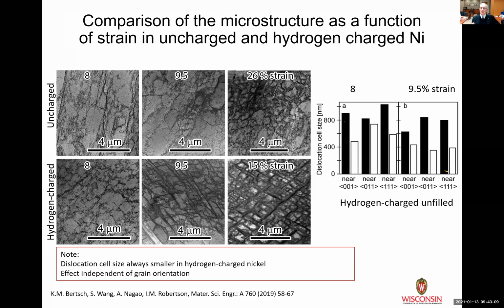You must compare microstructures in the same grain orientation. So one of the beauties that you have today is that you can do EBSD analysis in a sample. You can identify the grains and the grain orientations prior to deformation, because those orientations will change when you deform, but you can measure it prior, identify those same grains later and say, well, I know this grain started as near 001, or sorry, 011. So you can pick that starting orientation and you can compare them. And that's what we've done in these three images here.